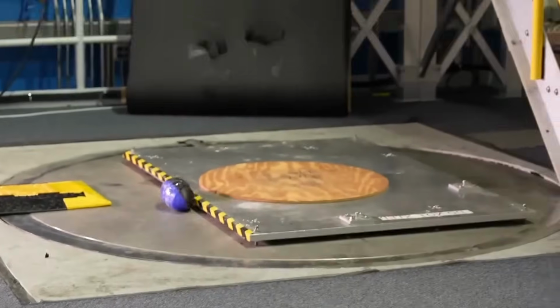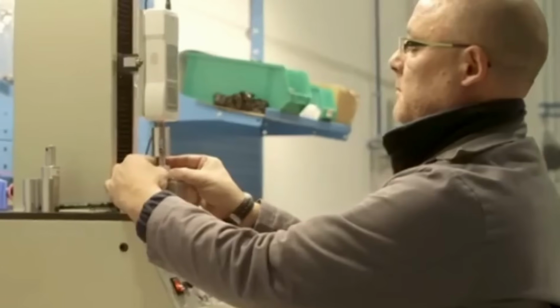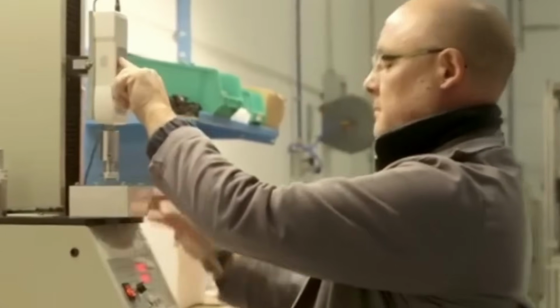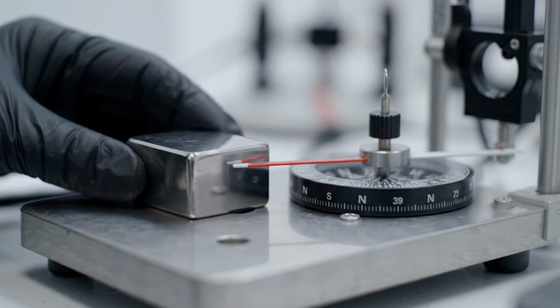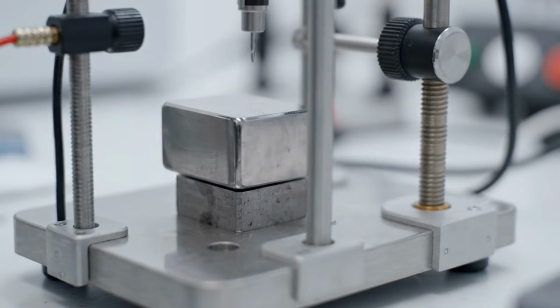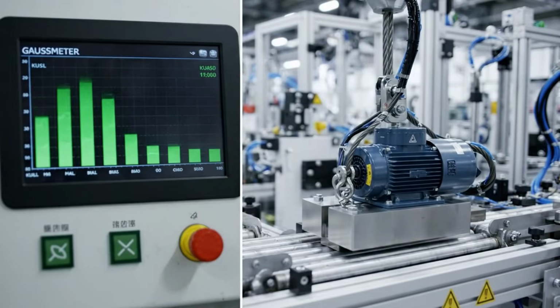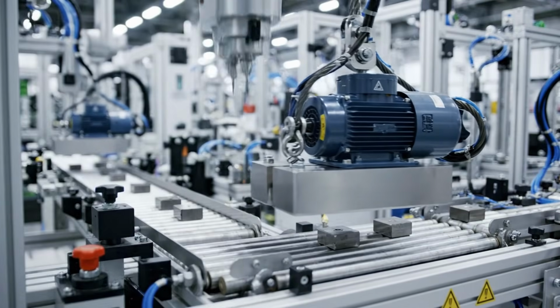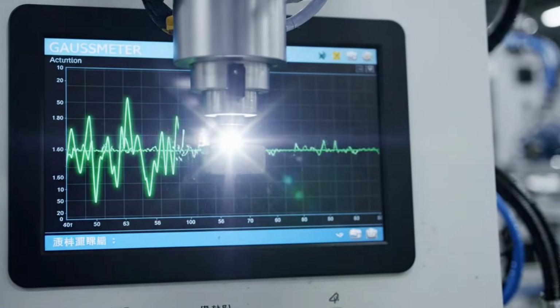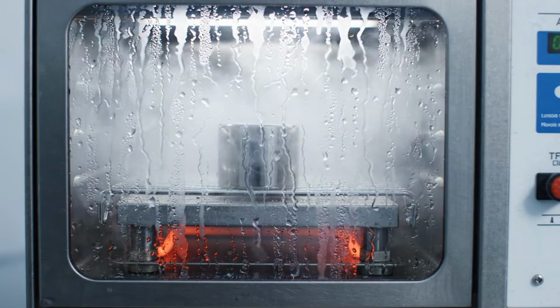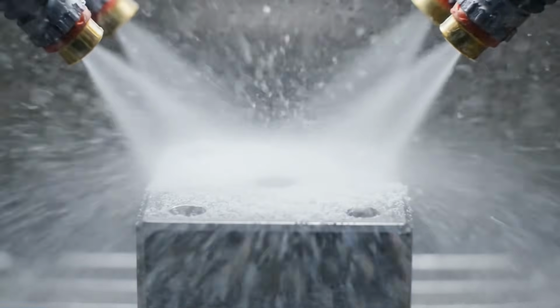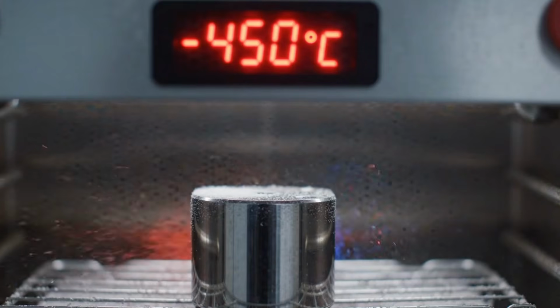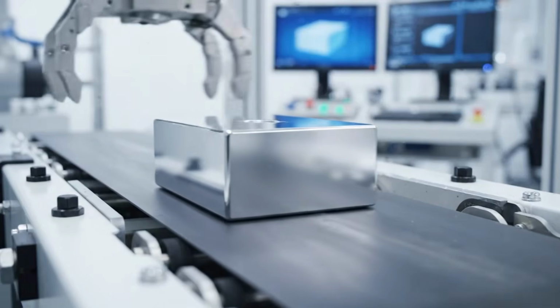In electric motors, turbines, and industrial equipment, this property is critical because the magnet operates near intense fields, vibrations, and heat. Each component is weighed using high-precision equipment. A minimal error in the proportions can change the final strength, thermal stability, or the ease with which the magnet loses its magnetism. In a mass production line, the materials are loaded into sealed mixers to prevent moisture and oxygen from entering. This protection is especially important in neodymium alloys because neodymium reacts readily with air and can oxidize. If it oxidizes prematurely, the material loses performance and develops internal defects.